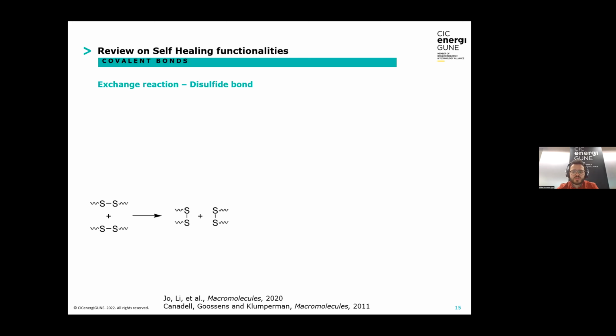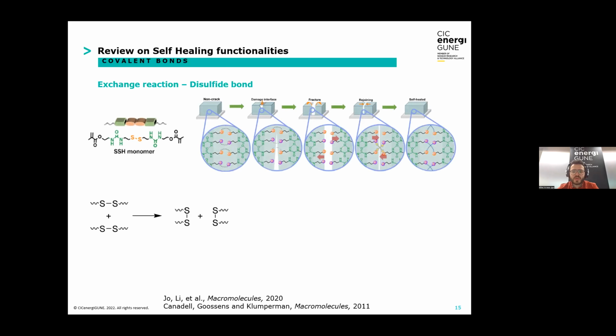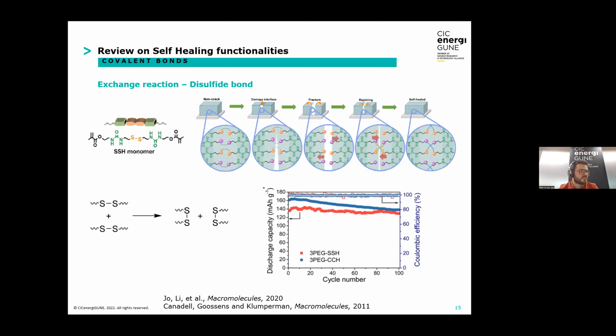In this example, these disulfide bonds are exchanged to reheal the polymer electrolyte membrane, and the use of these disulfide bonds allows to increase the battery life, as you can see in this figure, compared to only hydrogen bonding containing membranes. Self-healing via these disulfide bonds occurs at temperatures higher than the glass transition temperature of the polymer, therefore, it is ideal for polymer electrolytes, which usually operate under these conditions at temperatures above its glass transition temperature.